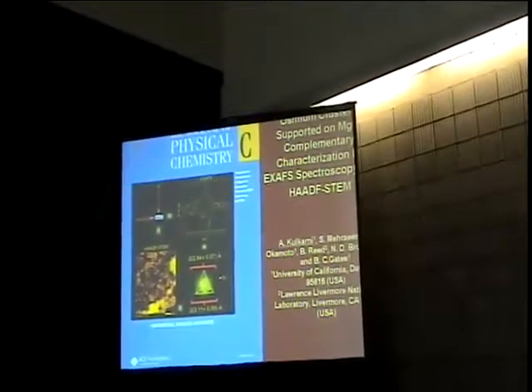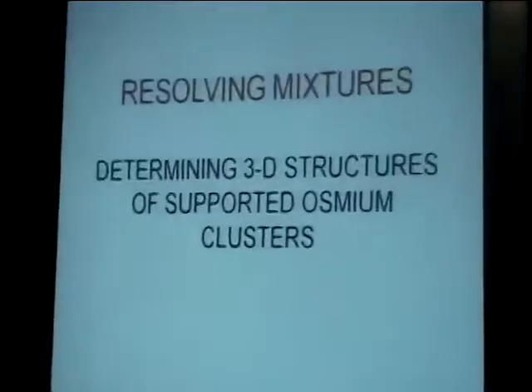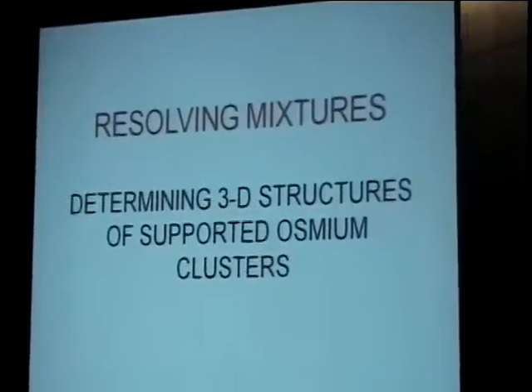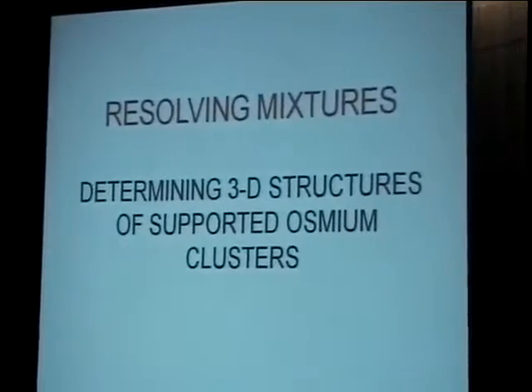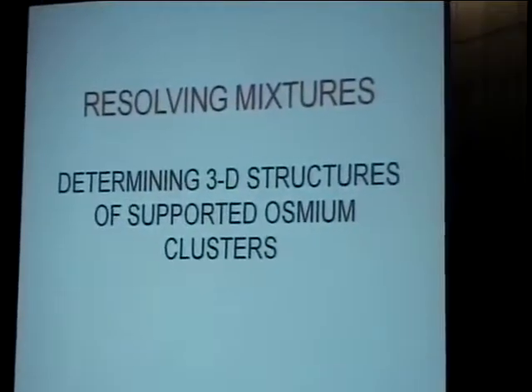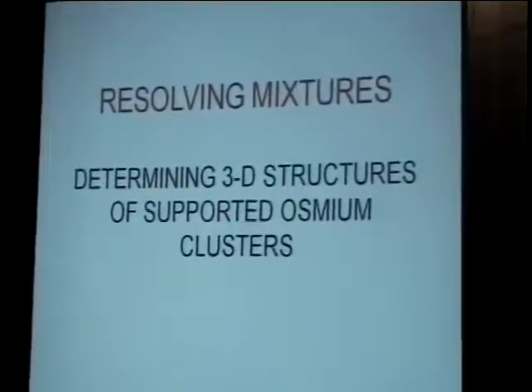And we do the microscopy and then obviously do the spectroscopy and get comparable values for the size, this radius 2 times that diameter of the cluster. So again, satisfying agreement between what this time is conventional microscopy, conventional STEM, not aberration-corrected STEM, and the spectroscopy. So we've made these in pretty high yield. Okay, so now the next step is to try to say, all right, suppose you've got a mixture of these clusters. What can you learn by microscopy and spectroscopy to try to resolve the mixture?